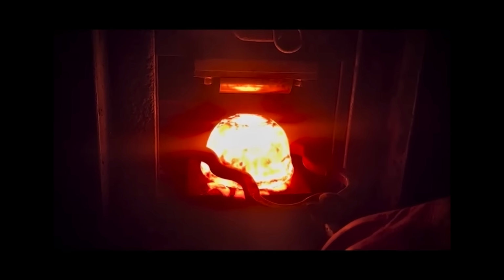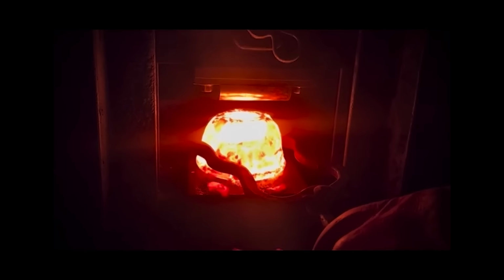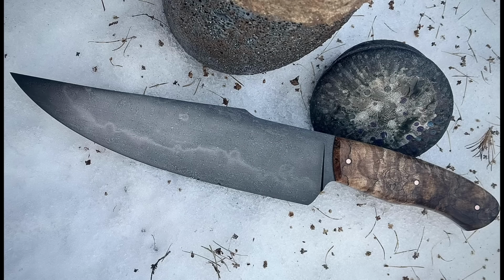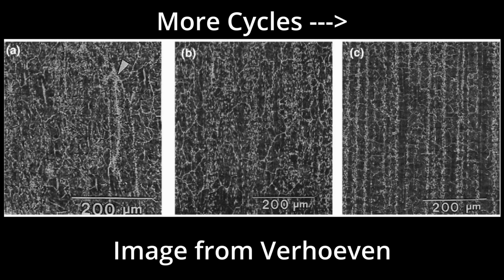He puts it in a furnace at 2900 degrees Fahrenheit and holds that until it melts, after which he slowly cools the crucible and the steel solidifies. Then he holds it at high temperature, called a soak, and then he forges it down. The thermal cycles that the steel goes through during the forging lead to the final carbide banding.